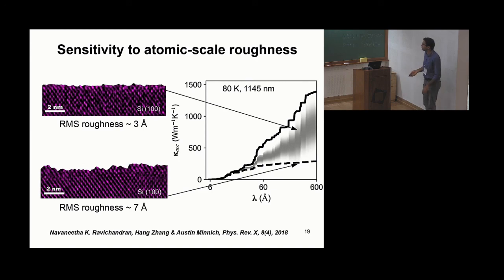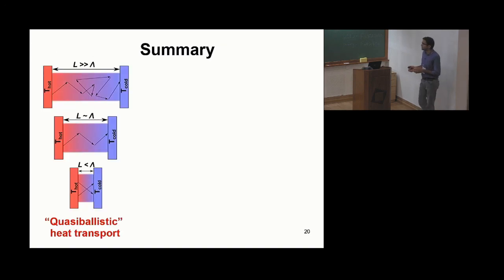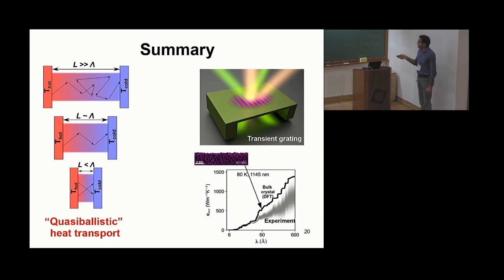So in summary, I hopefully explained how to get phonon-specific, mode-resolved information from an experiment by using a non-diffusive heat conduction regime, going from a diffusion to a ballistic kind of heat conduction regime. I explained the experiment that can really do this transition from diffusion to ballistic transport, and with that, how we are able to measure boundary scattering of phonons in nanoscopic thin silicon film.